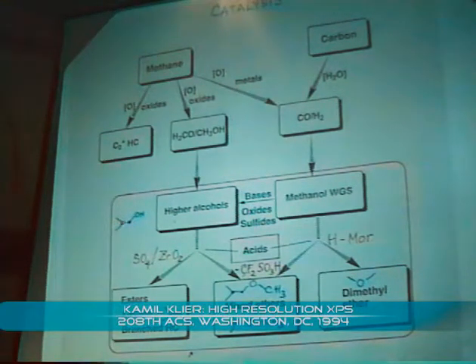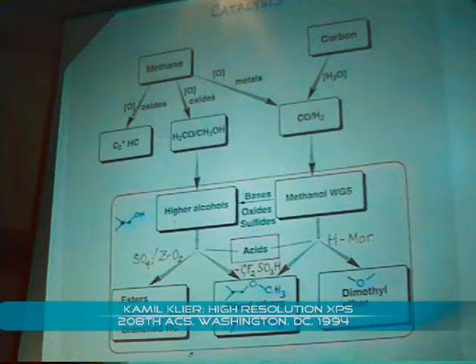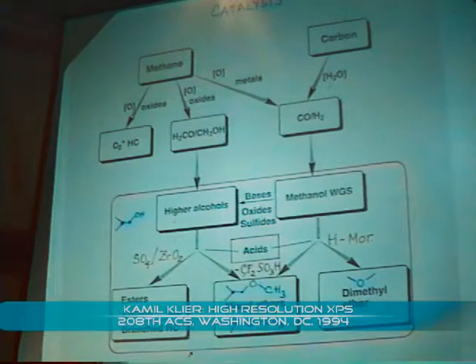Isobutanol can couple with methanol to methyl isobutyl ether. The selective catalyst for that is Nafion H, a fluorocarbon sulfonic acid. If we use the shape selectivity of side pockets of H-mordenite, we get selectively dimethyl ether without touching isobutanol. Even though isobutanol has access to large channels, the protons in those channels are quickly poisoned. All of these reactions occur at fairly low temperatures, certainly below 180 degrees or most commonly 150 degrees centigrade, and rarely above 200 degrees centigrade.